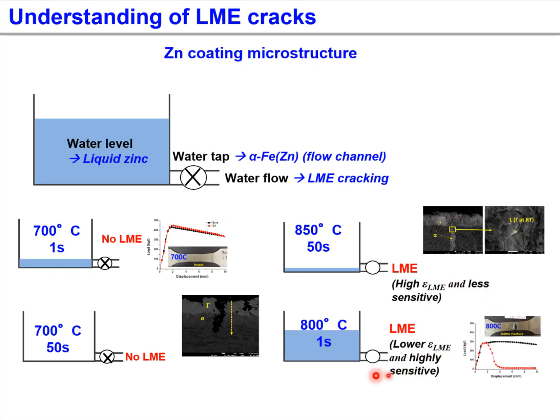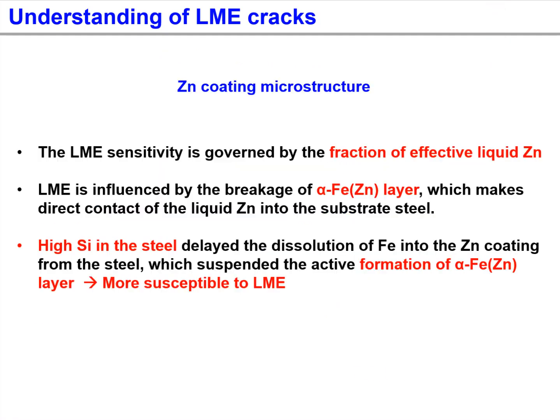For a similar case, the 800 degrees Celsius, 1 second hold time condition provides a large fraction of liquid zinc and a continuous alpha Fe zinc layer. The following is a summary of the effect of zinc coating on LME cracks. The LME sensitivity is governed by the fraction of effective liquid zinc.